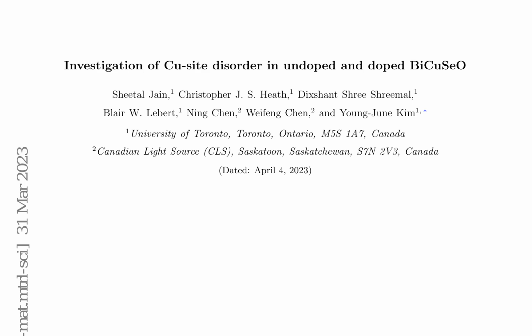X-ray diffraction, XRD, and extended X-ray absorption fine structure, EXAFS, results for Cu in BiCuSeO at 150 K are presented, with XRD data shown in Figure 3b. Unlike an earlier neutron diffraction study on undoped BiCuSeO, which reported a strong temperature dependence of anisotropic atomic displacement parameters, ADPs, the displacement parameters for Cu do not exhibit significant changes below room temperature. Due to the large uncertainty associated with estimating anisotropic parameters from diffraction data, it was decided not to estimate these parameters.